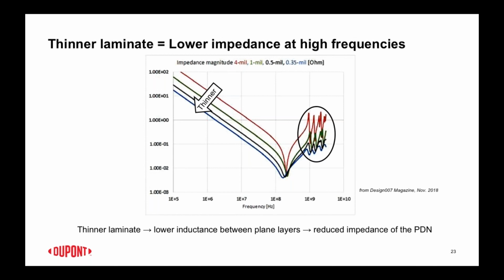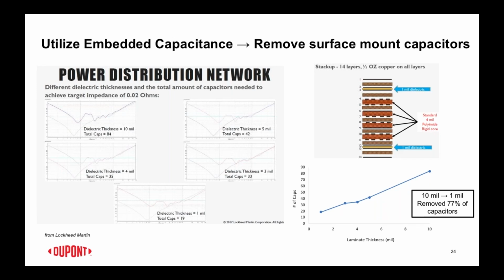This is the sub couple of hundred megahertz range. Then you take it to its inflection point, which is typically in the 300 to 400 megahertz range, and then it actually becomes more about the inductance. And there, the thinner also gives you better performance when you get into the higher frequency ranges. So at this point, I'd like to say what's really happening by making these thin power ground planes is, we call it embedded capacitance, but really it's somewhat of a misnomer, because what we're really doing is lowering the overall impedance of the distribution network by lowering the inductance.